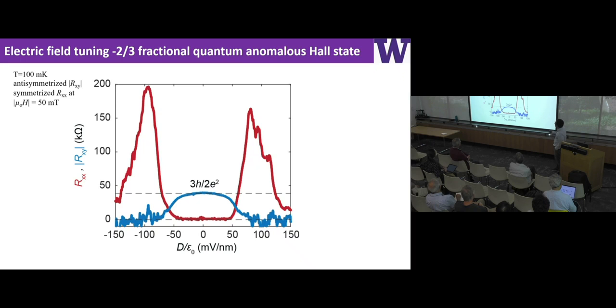And we can also use electric field to control the phase transition from this fractional quantum anomalous Hall state to a topologically trivial state. What I show you here is the electric field dependence, and the blue curve is Rxy, where you see Rxy quickly drops and vanishes. And we see the Rxx was initially nearly vanishing, then increases, seemingly to an insulating state, then drops again, seemingly to another metallic state. So we don't know exactly the nature of this state. It's still under study.